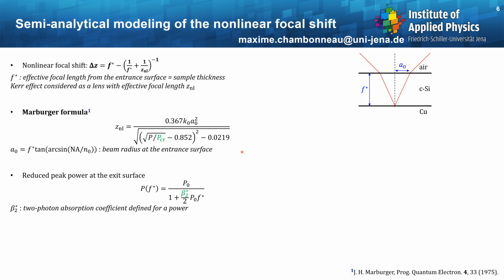ZNL is further defined by Marburger's formula in this equation here, where k0 represents the wave number, a0 represents the beam radius at the entrance surface, PCR is a first fitting parameter, and it is the critical power for self-focusing, and P is defined here in this equation on the bottom. It is the reduced peak power at the exit surface of the silicon sample, where P0 is the input power, and beta 2 star is a second fitting parameter, which is the 2-photon absorption coefficient defined for a power.